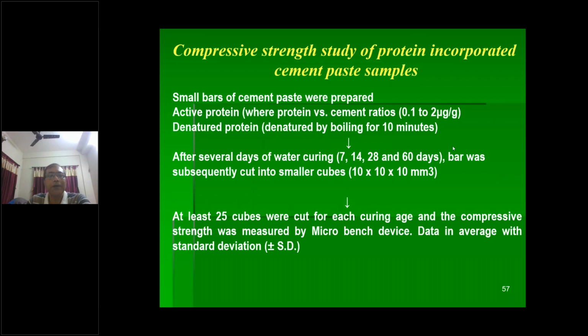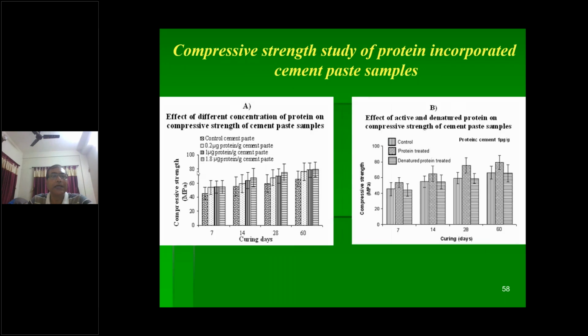Now we have also done a compressive strength study of the protein incorporated cement paste in a similar manner. We studied the control paste, then 0.2 microgram protein per cement, 1 microgram protein per cement, and 1.8 microgram protein per cement. We get similar results: if we increase the protein percentage, the strength is higher. Similarly, here is the protein treated and here is the denatured protein treated. So we get higher strength if we add protein to the cement based sample.